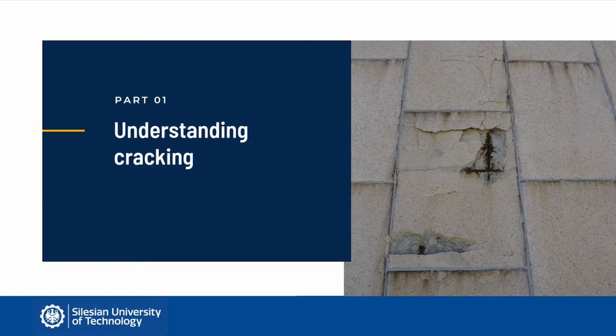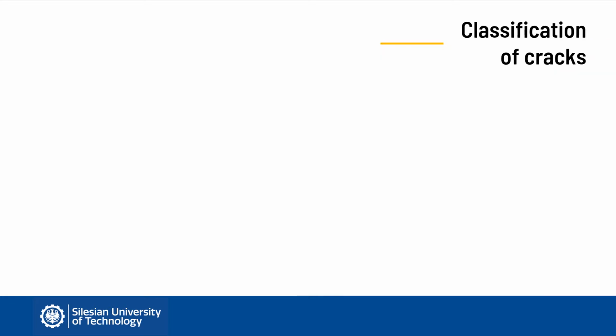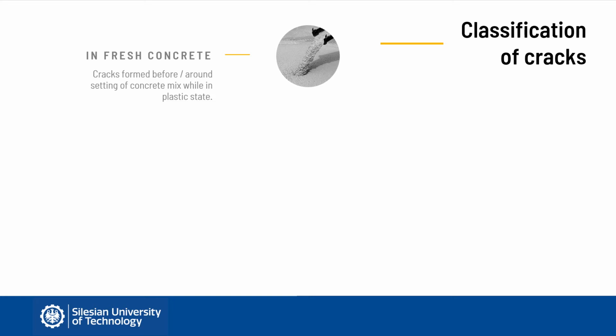This being said, let us start with shedding some light on the background of cracking in reinforced concrete. In general, concrete cracks because it is a brittle material when subject to tensile strains. Nevertheless, cracks which can be formed throughout the whole life of the structure may have different origin, behavior, and effects on the structures. The cracks may form as early as in the fresh concrete, around the time of setting, when concrete is still in plastic state. This early damage to concrete is usually manifested by a pattern of hairline cracks visible on the surface of the element.